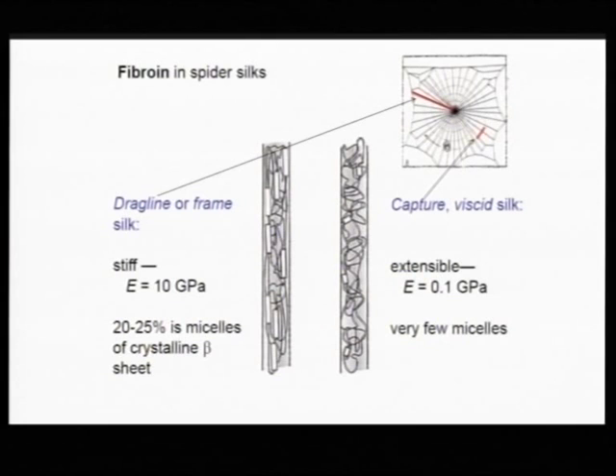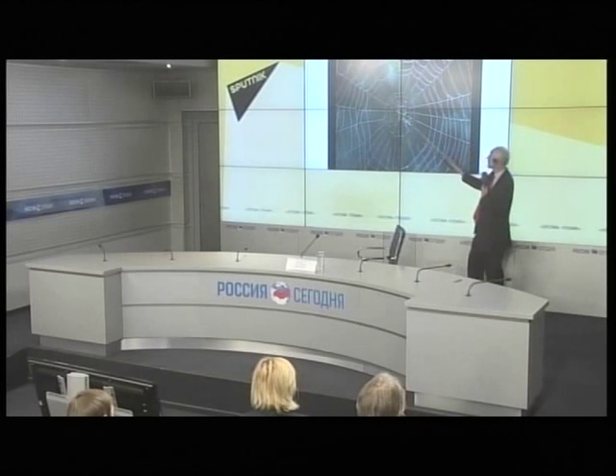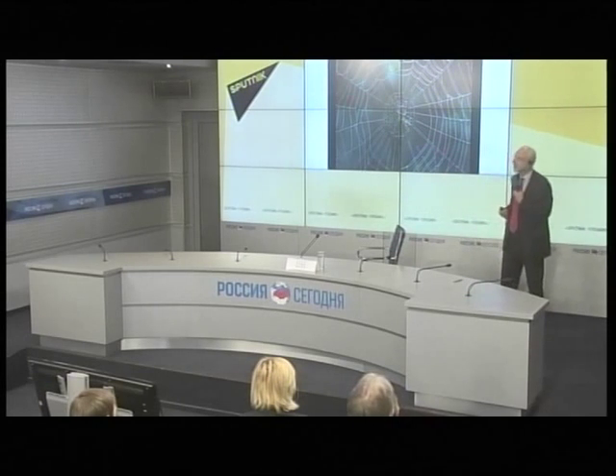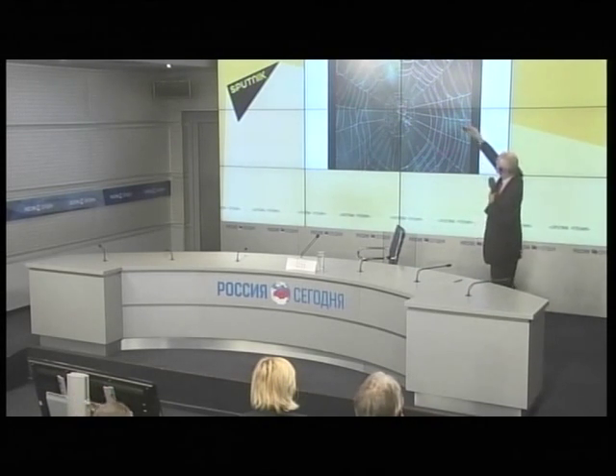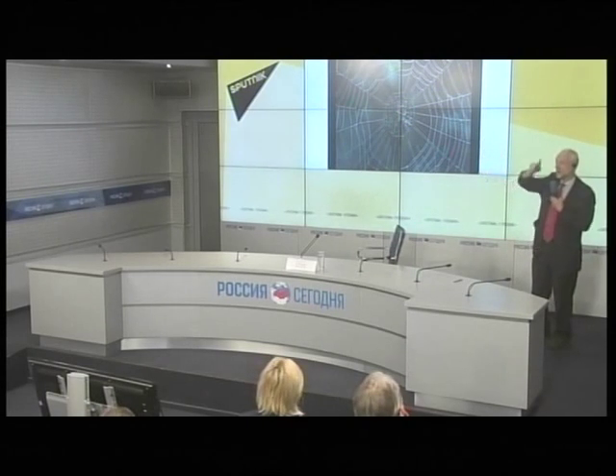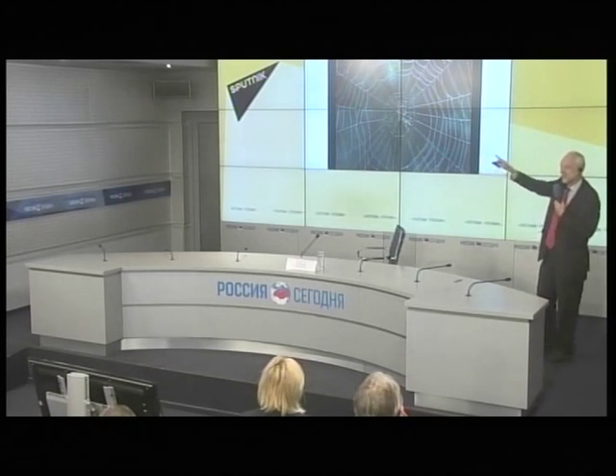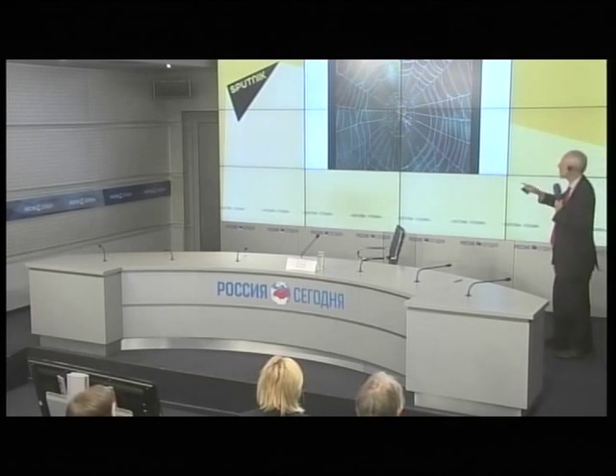It achieves that by allowing the polymers here, the long chains, to be more or less independent of each other, whereas here they're linked into crystalline structures bound locally to make the overall material stiffer. So here's the web. These are the stiff lines of high modulus, 10 gigapascals, and these are the capture lines of low modulus at 0.1 gigapascals. In fact, if you look at those capture lines up at the top, you'll see that they are not straight. They're hanging under their own weight, so low is the modulus. They're stretching under their own weight.